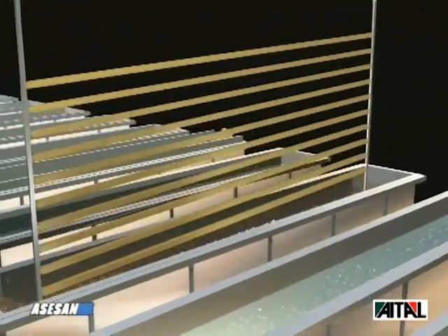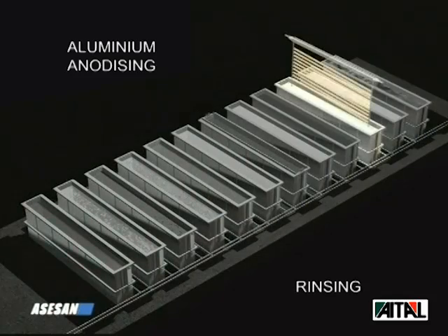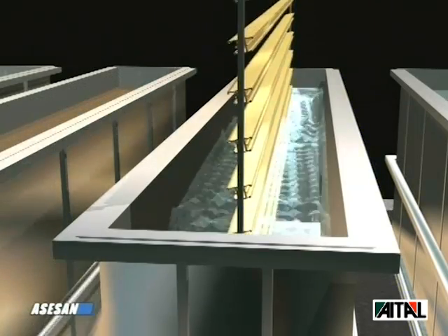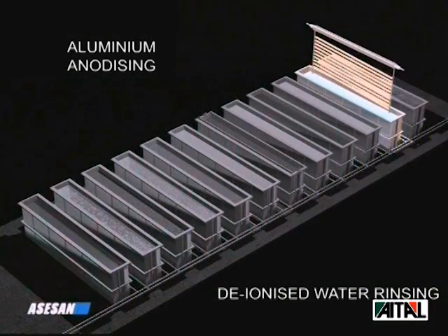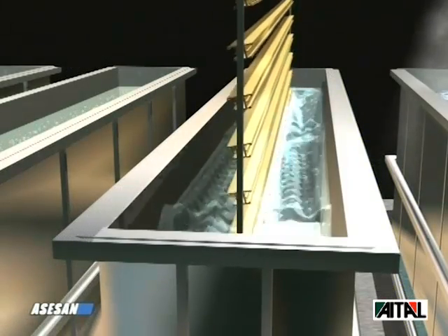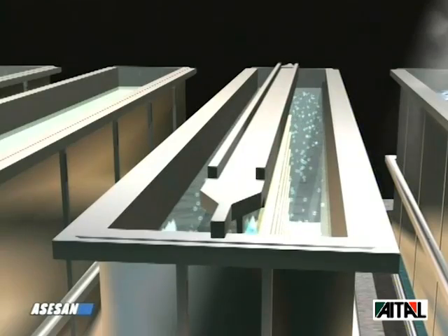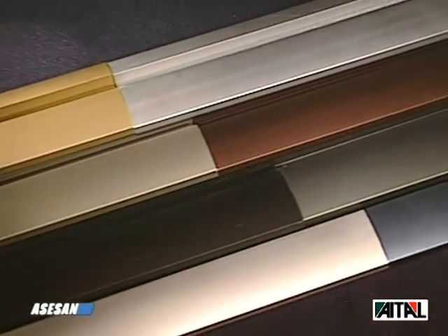When the anodic layer is formed and the coloring process is complete, the pores must be sealed with a sealing treatment. First of all, a careful rinsing with water is essential. A second deionized water rinsing follows to completely remove any acidic residue from the pores. Finally, the porous structure must be sealed. This is an extremely important step to obtain the highest levels of resistance to corrosion of the anodic layer.